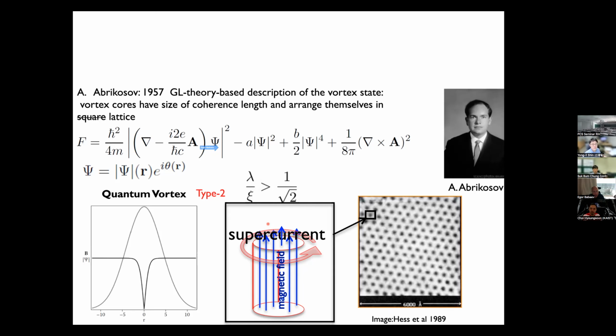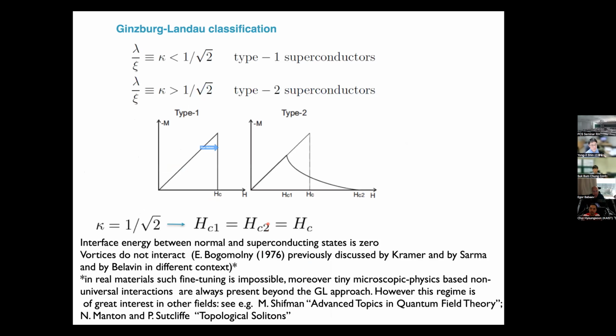And here another thing is that there is a first critical magnetic field, a concept that first appeared in Abrikosov: the magnetization of a superconductor actually has two critical fields. First where vortices appear, and second where superconductivity disappears. And these are all second order phase transitions. So in the magnetization of a superconductor, at first superconductors display a perfect diamagnetic response, with currents only on the surface. And then vortices penetrate and the magnetization drops, the magnetic response becomes weaker, and so there is this type of phase diagram.